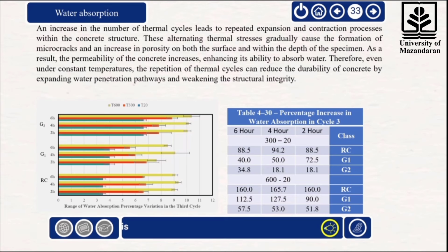Increasing the number of thermal cycles from 1 to 3 induced repeated expansion and contraction within the concrete structure. These alternating thermal stresses gradually produced microcracks and increased both surface and internal porosity, thereby raising permeability and water absorption. Thus, even at constant temperatures, repeated thermal cycling can reduce concrete durability by creating additional pathways for water ingress and weakening the structure. The table corresponding to 3 cycles shows that water absorption increased in most specimens.